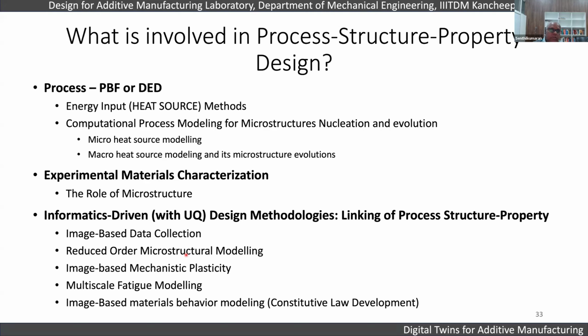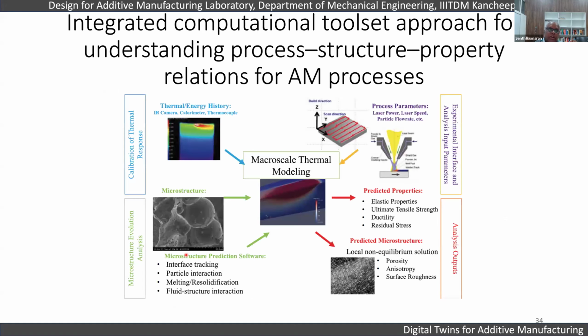And when you do the integrated approach, like for example, when you are integrating the computational tool set approach, right? So we need to understand the process structure. For example, first one is calibration of the thermal response. Second is the microstructure evolution analysis, and then the experimental study of the process parameters. And we have to then create a macro scale thermal modeling. From that, we have to predict the properties like ductility, residual stresses, UTS, and elastic property. And also from the non-equilibrium solutions, local non-equilibrium solutions, you have to also understand porosity, anisotropy, and surface roughnesses and all. So you can see that it is a very involving, much complex teamwork that needs to be built to basically do it.